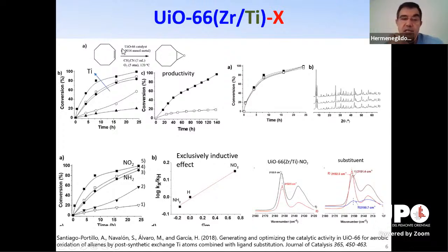This is our best model, cyclooctene, because it's convenient, volatility is low, and it's very easy to determine the formation of the product. And depending on the titanium that you have, the activity increases, and in this case we can go up to an exchange between zirconium and titanium of about 40%. Maybe if we go further, then the activity increases even further. The material is stable, and here we have a productivity test in which we run the reaction for a very long time with just a small amount of catalyst, and we observe an increase up to a complete conversion. Also here we have a recyclability test, and as you can see, the temporal profiles coincide. Also the XRD shows that there is no change in the material.